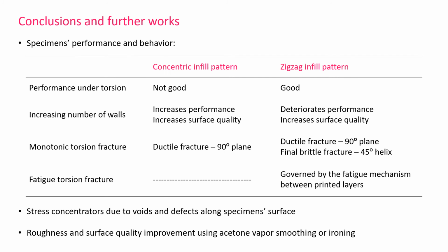Conclusions. In this work, the fatigue response of an improved set of fused filament fabrication ABS solid cylinder specimens under monotonic torsion tests was evaluated. From monotonic tests, it was concluded that the zigzag infill pattern leads to better mechanical properties under torsional loadings when compared to the concentric infill pattern. Increasing the number of walls proved to be beneficial for the concentric pattern, while it reduced the zigzag pattern's performance.